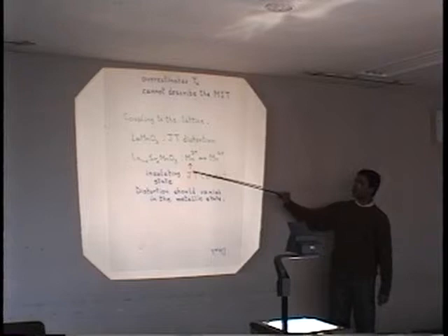And we wanted to investigate if indeed there are distortions and what kind of distortions are there. And we carried out some experiments, extended absorption fine structure, EXAFS experiment, which probes the local manganese oxygen distances.